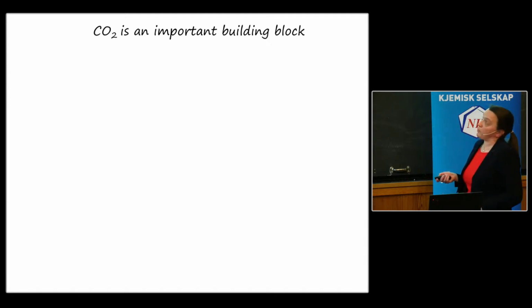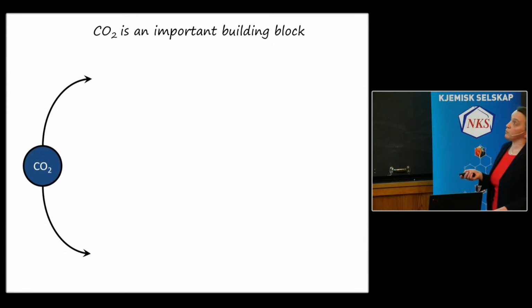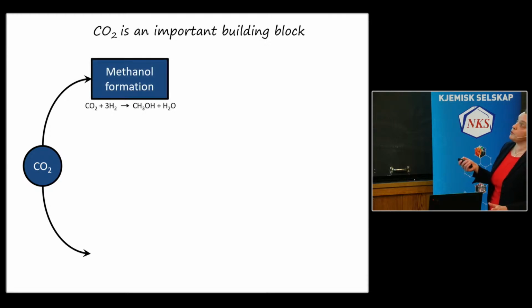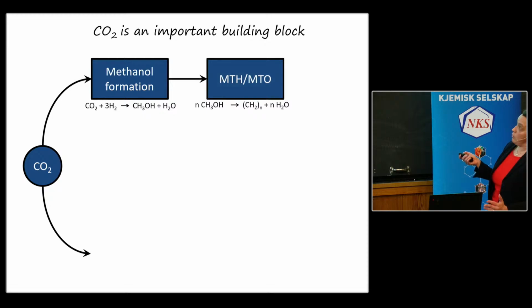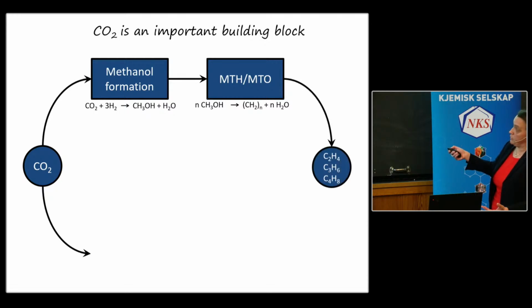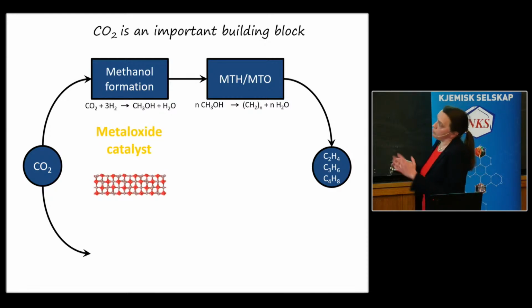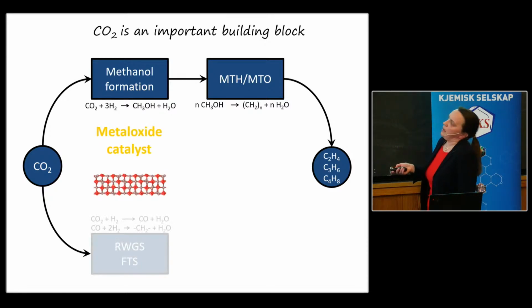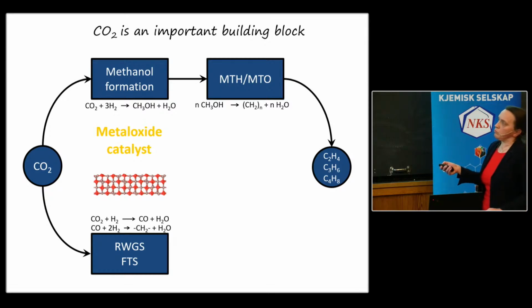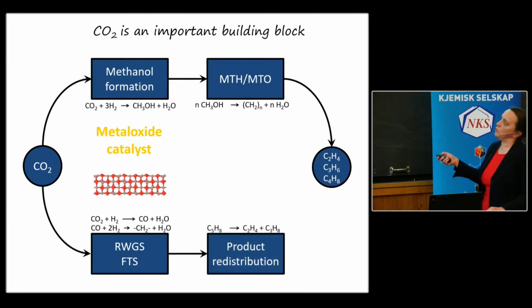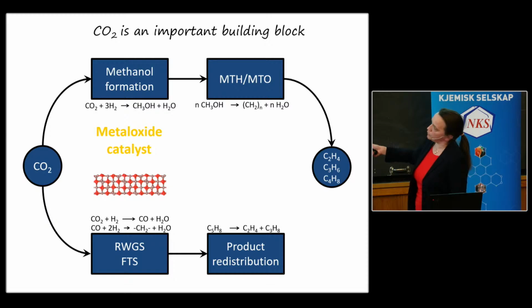And that is something that is explored. So basically, if you start from CO2, you can convert CO2 first to methanol. And then from methanol, you can indeed go further with the zeolite catalysis, with the MTH or MTO process, and you can make the hydrocarbons here. With the CO2, here you, of course, need the metal oxide catalyst. You can also start from the CO2, do the reverse water-gas shift reaction, and then do the classical Fischer-Tropsch, and then we can also try to tune the product distribution that you receive from Fischer-Tropsch with zeolites, and also make selectively the hydrocarbons that we want.